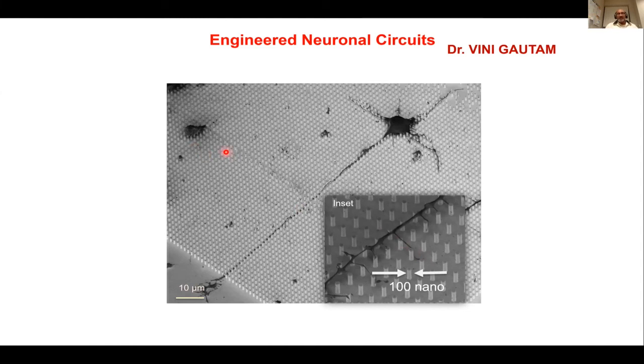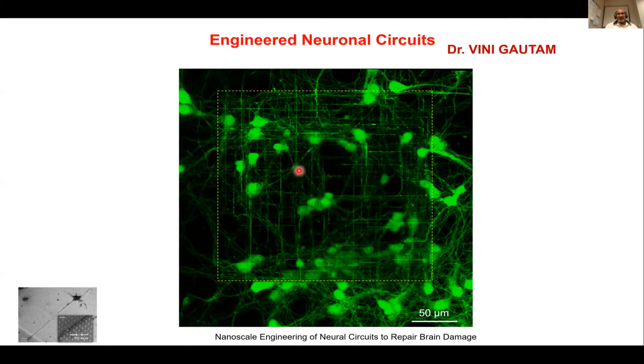So instead of using a single neuronal cell, what will happen if you put multiple neuronal cells? You can see that if you do that, this dotted box is where the indium phosphide nanowires are. You can see the many neuronal cells here, and these axons really follow these square patterns beautifully. Whereas on the flat indium phosphide outside this region, neurons are growing, but they're all making random connections. So that means there is some sort of neuronal engineering taking place by using these nanowire arrays.